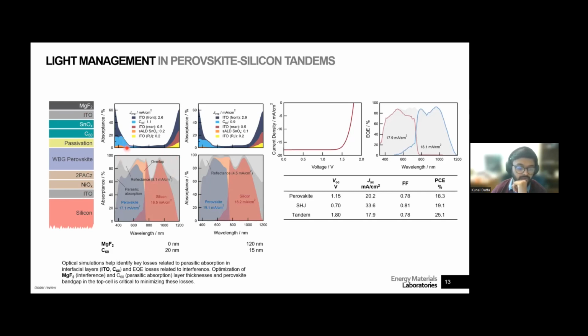And if you split up the parasitic absorption, you can quite clearly see that most of it is coming from this ITO layer. So this is the equivalent of the JSC loss that you're having in your device. So most of it is coming from the ITO layer, some of it is coming from the C60 layer, and the rest of it is a bit less important to the parasitic absorption. The other bit is, of course, the reflection, because you're losing 8.1 milliamps from just reflection.